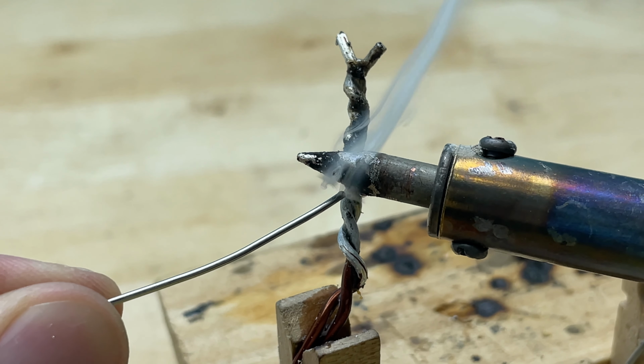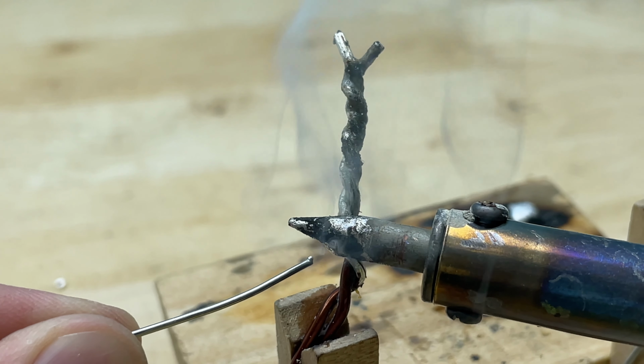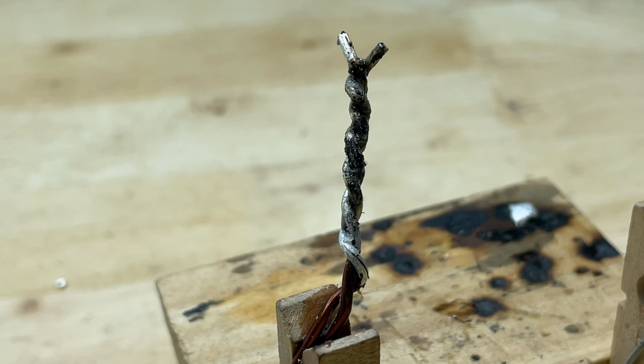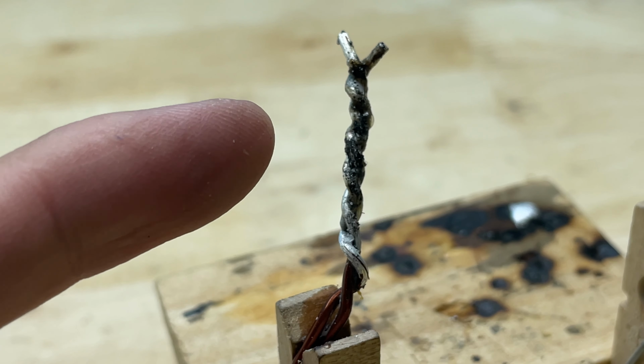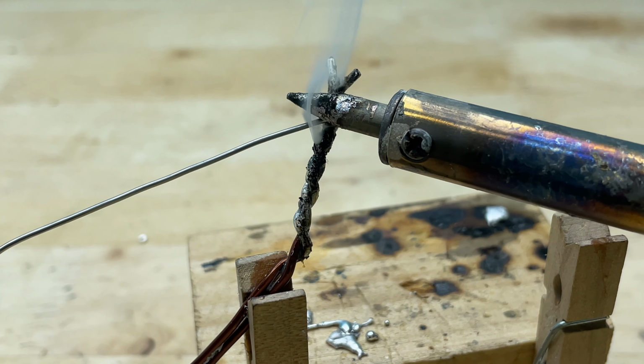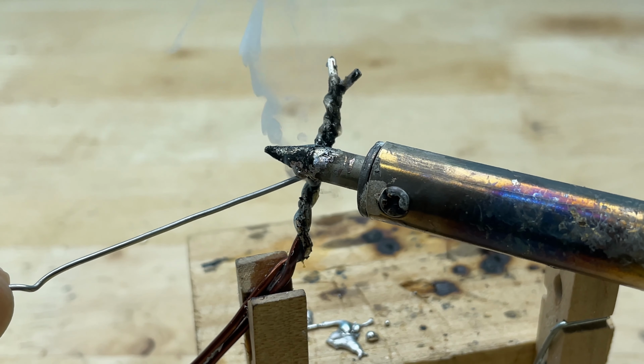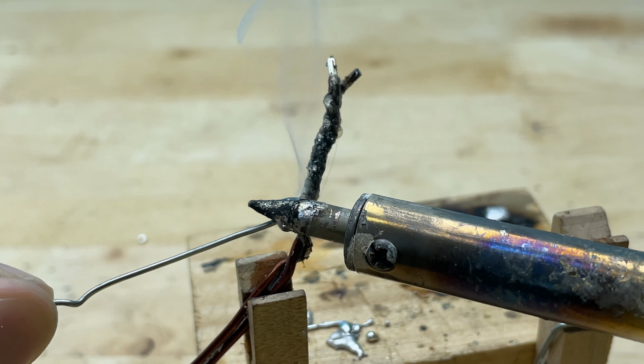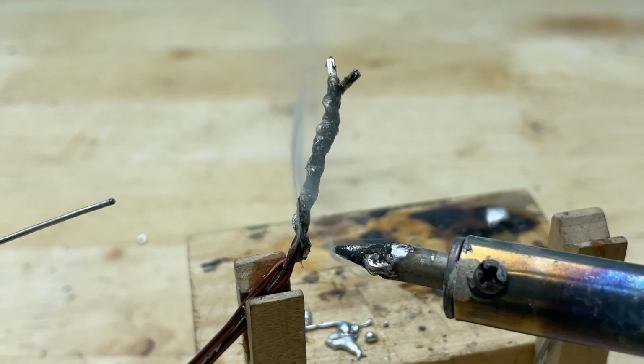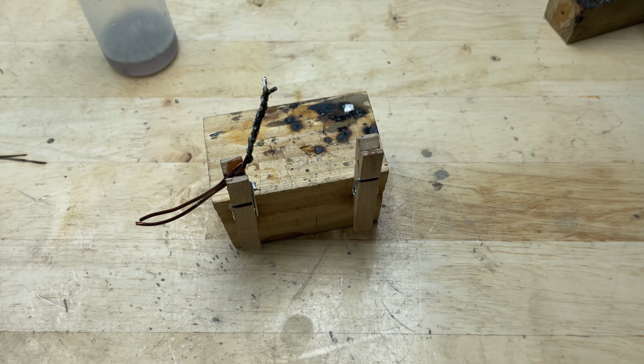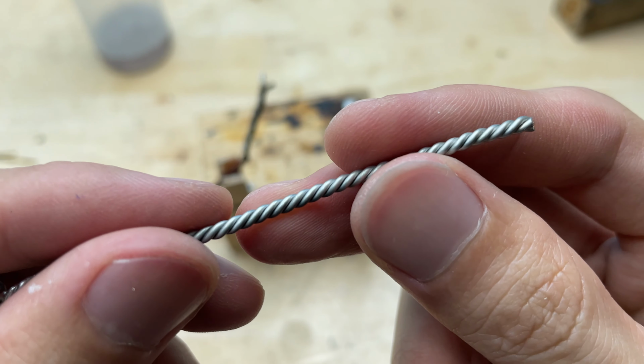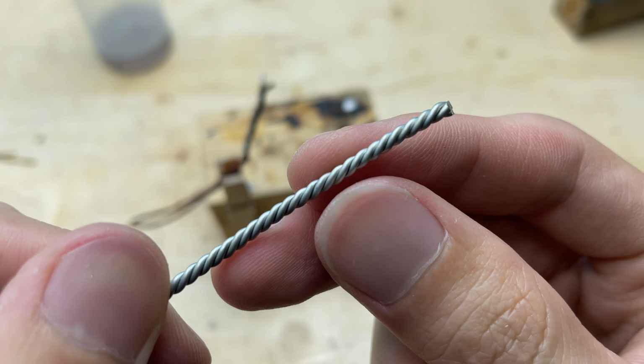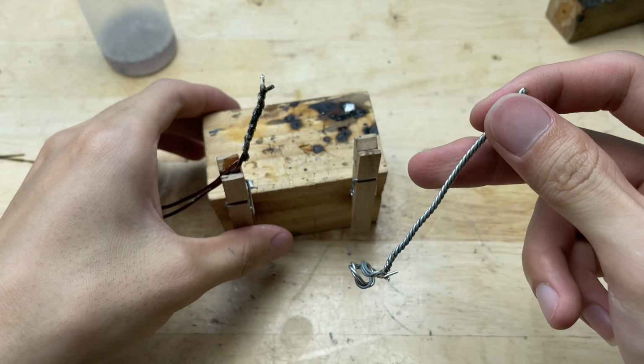The tin spreads smoothly and forms a solid, shiny joint that clings tightly to the surface, indicating a strong bond. Unlike before, there are no gaps or signs of solder peeling off, showing that the homemade flux did its job in preparing the metal for a successful weld. Next, I'm going to solder 2 pieces of steel wire.